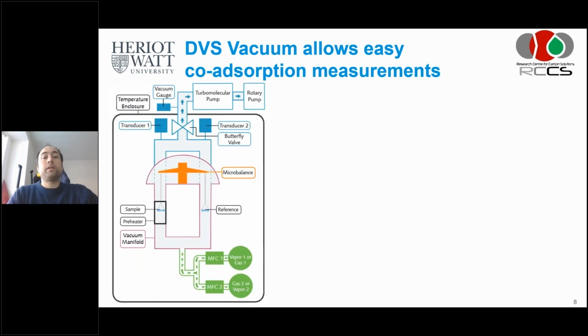So now about the DVS vacuum, it allows easy co-adsorption measurements if, and that's an assumption that has to be tested first, water is not displaced by CO2. So that's an important assumption. So what you can do, and I'll show that later, if you know that water will not be displaced by CO2, you need to establish that, for instance, with breakthrough experiments before you do this kind of analysis. But what you can do then is load water onto the sorbent and then in small steps add CO2. So that means that you know how much water has been taken up on the adsorbent, and then you can also measure with the gravimetric balance how much additional CO2 is taken up.